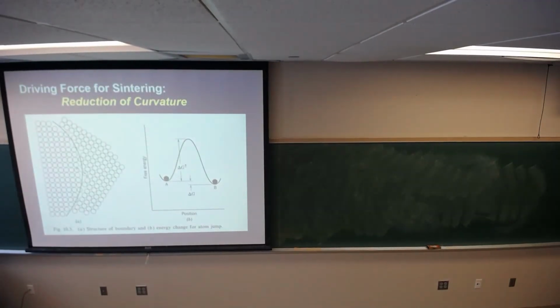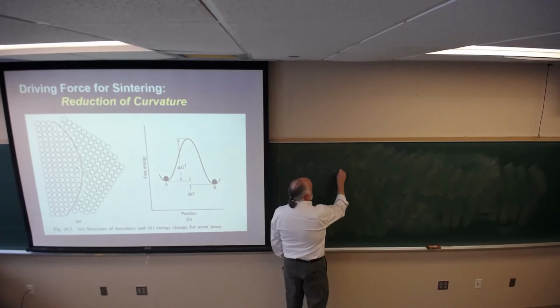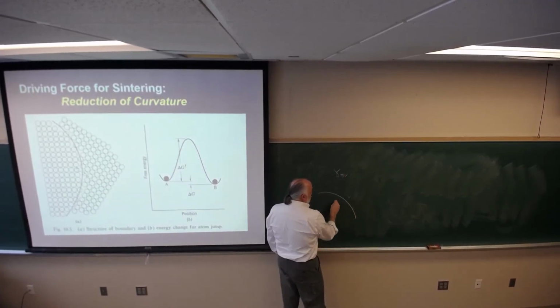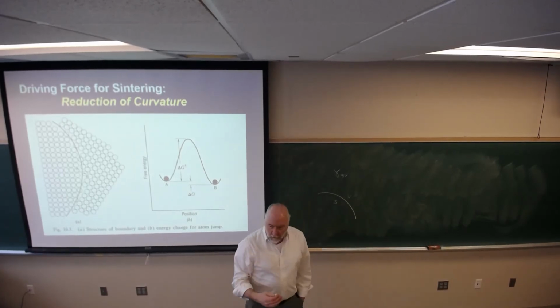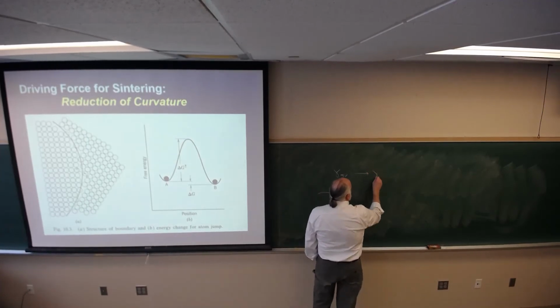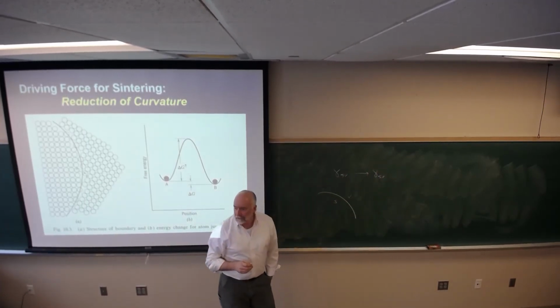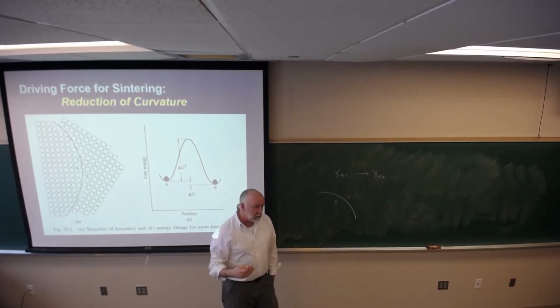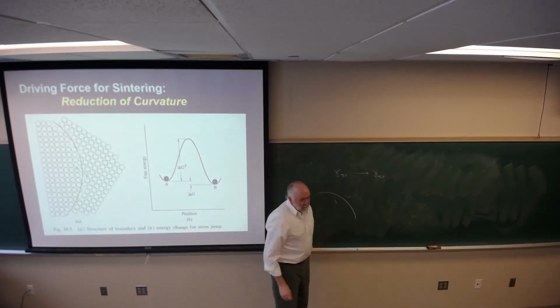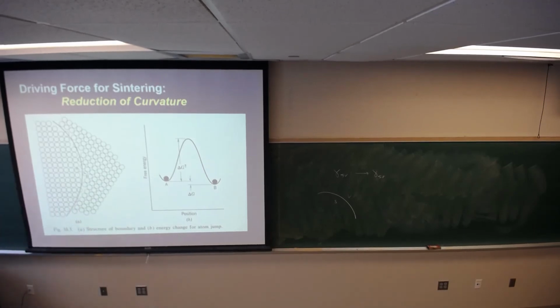The whole thing, driving force for sintering, okay, reduction of curvature. You could equate that argument to surface area. The more surface area you have, the greater the driving force for sintering and densification. Okay, so what we have is you have a surface energy term, gamma SV. So you have a free surface, you have a vapor out here, you have a solid here, and it's that surface energy. What you're doing is you are exchanging that surface energy, reducing it by converting it to gamma SS. I assume you heard about this in thermal. Well, that's good. So your solid-solid interfacial area is typically lower than your solid vapor interfacial area. And thus, there is a driving force to reduce the energy by forming solid-solid interfacial area, grain boundaries, instead of having that solid in contact with the vapor.